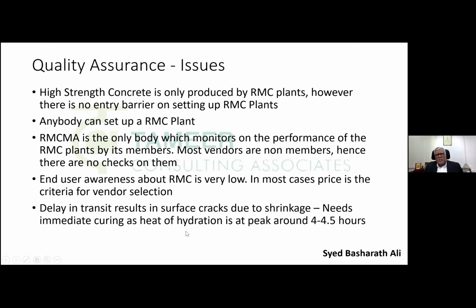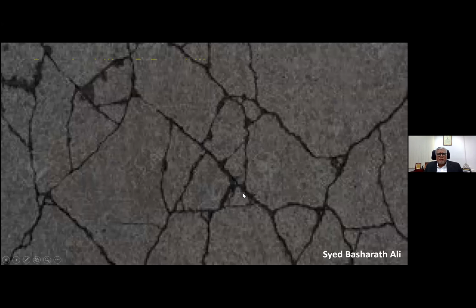And then again, delay in transit results in surface cracks due to shrinkage. In many places we notice that concrete is placed beyond 4.5 hours after being charged into the transit mixer at the RMC plant. This concrete starts setting very soon, and if curing is not initiated immediately, then you will see surface cracks on account of shrinkage, which have to be attended to immediately.